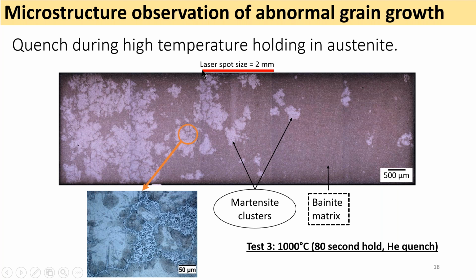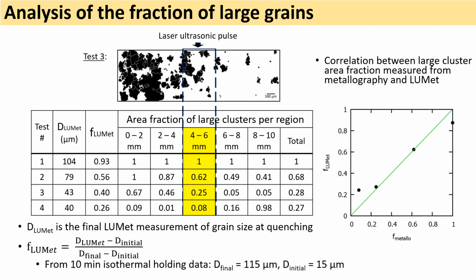And what you can see here is that depending on where we would measure the austenite grain size, we may not have the same average grain size in the bulk of the sample. So what we have done here is estimate the area fraction of large grain size in this sample. So what you see here are slices between 0 and 2 millimeters. The fraction of large grains was about these values. And where we would measure the sample, we would have a different fraction of large grain size.